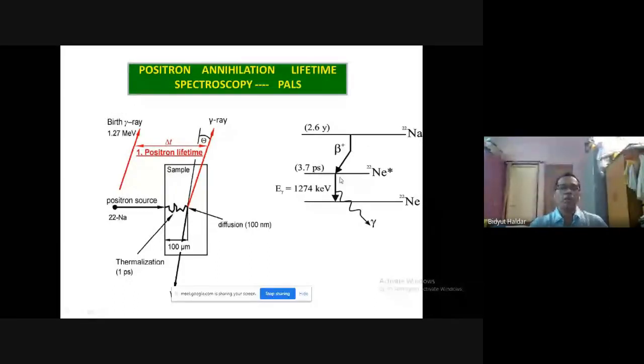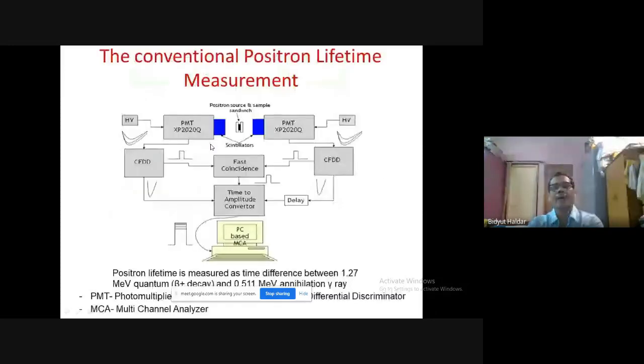The positron, after entering into the material, quickly thermalizes, and then it annihilates with the electron present there. In about 99.7% of cases, this electron-positron pair annihilates and usually gives rise to 2 gamma rays, which move in opposite directions in the center of mass system. If one of these gamma rays can be detected, the detection of one of these gamma rays announces the death of the positron. So by finding the difference in time between the detection of this gamma ray and the detection of the annihilating gamma ray, one can find out the lifetime of the positron inside the matter.